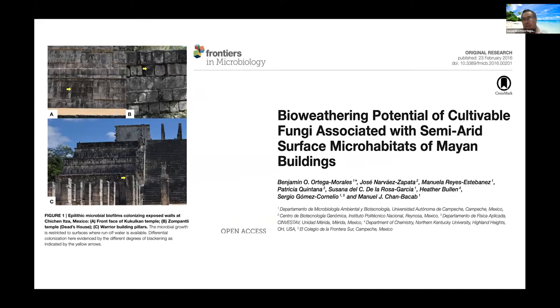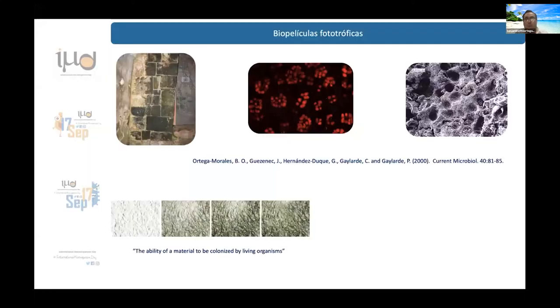We have been studying the potential of fungi and other microbes in the bio-weathering and biodegradation of limestone surfaces — the main building material the Maya used to build their magnificent culture. To give you perspective, about 800,000 people still speak Mayan as a first language. When biofilms grow over surfaces they can degrade limestone, and there is an important concept called bioreceptivity — the ability of a material to be colonized by living organisms.